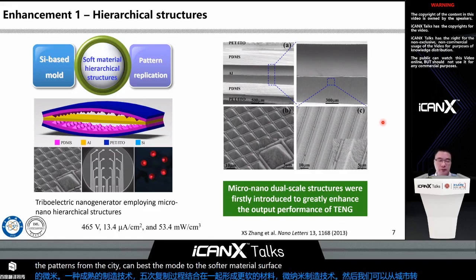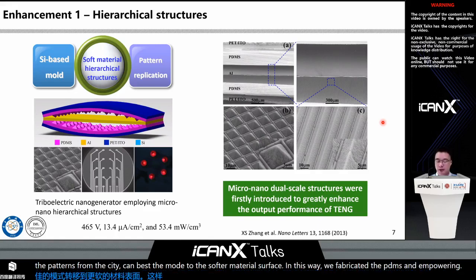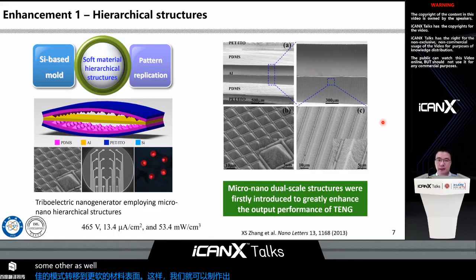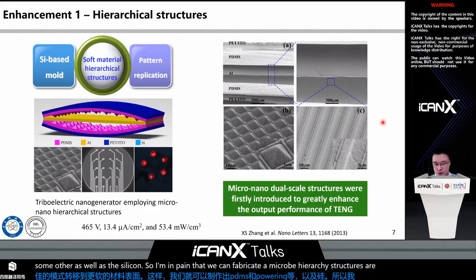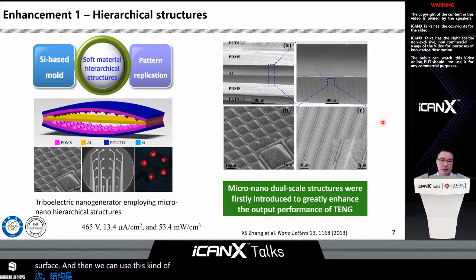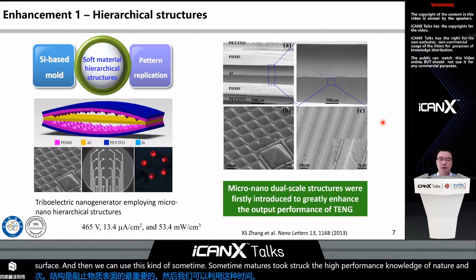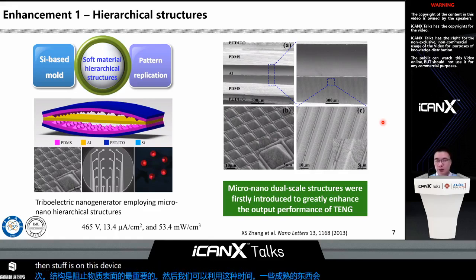In this way, we fabricated the PDMS and the Parylene and some others, as well as the silicon. So it means that we can fabricate the micro-nano hierarchical structures atop the softer materials surface, and then we can use this kind of softer materials to construct the high-performance nanogenerator. And then the surface of these devices can be maximally enlarged.